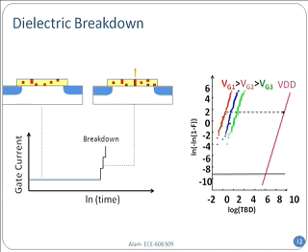First, let's look at the red one, VG1. And on the y-axis, I have F, capital F. F means fraction of the oxides broken. So that means, let's say you start with 100 transistors. The first one breaks. So the F is 1 divided by 100. This is a cumulative failure. Then the fifth transistor breaks. So F is 5 divided by 100. So on the y-axis you note when the transistor broke, and in the x-axis evaluate that function.